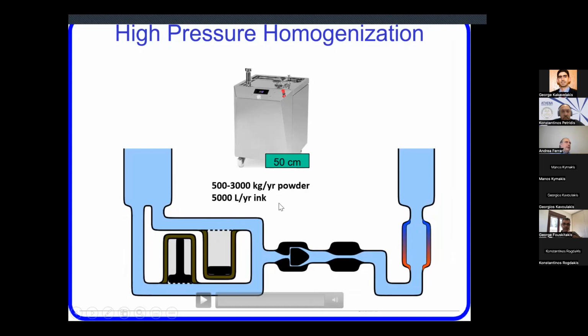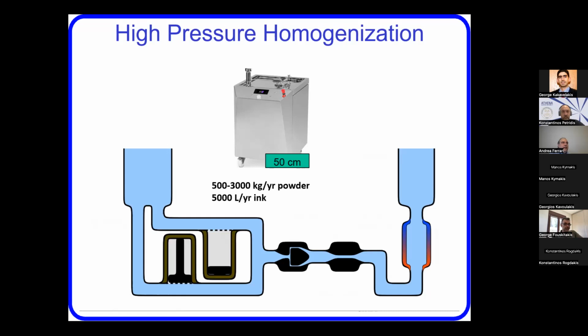But most importantly, this process gets nearly 100% yield. So all the graphene that you put in is exfoliated. You don't throw anything away, while in the process we developed in 2008, 99.2% of the graphite was thrown away. So again, this now gives rise to large-scale production and so on. Once we crack this, this opens up to different kinds of applications.